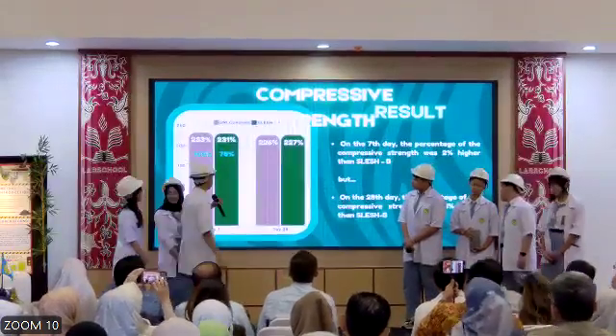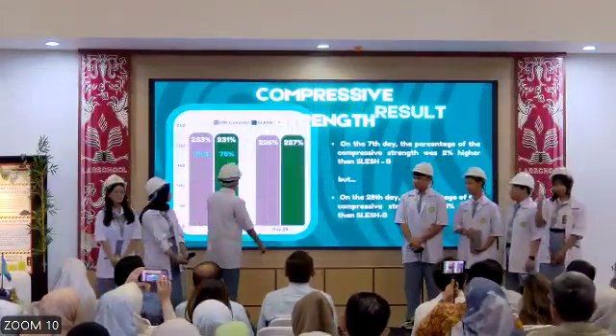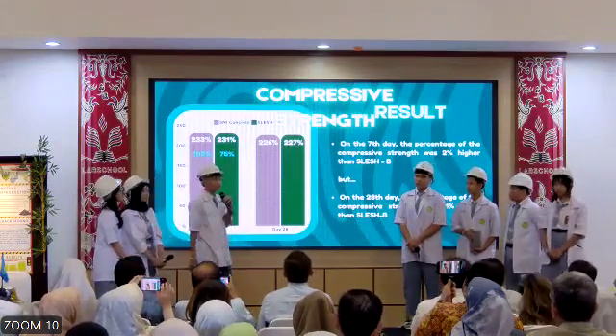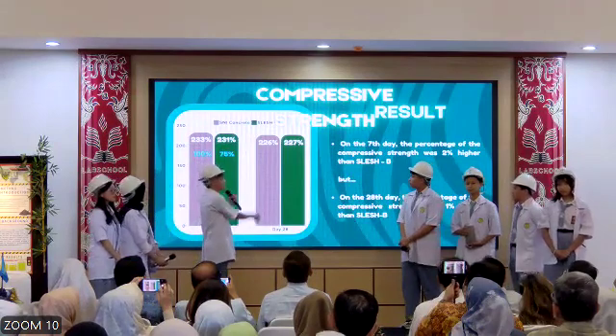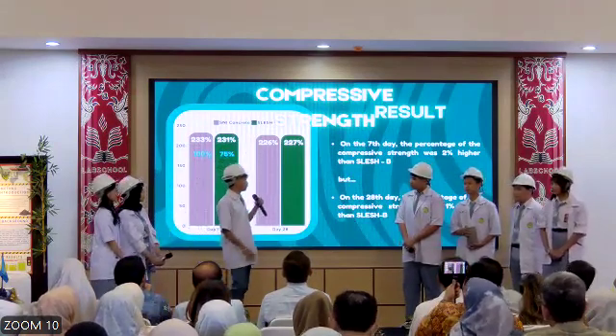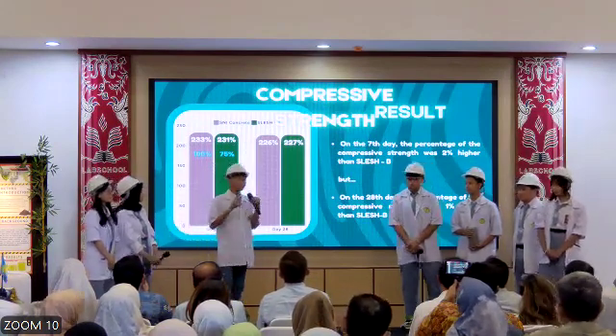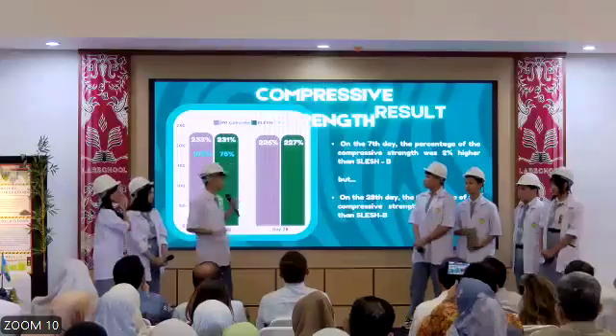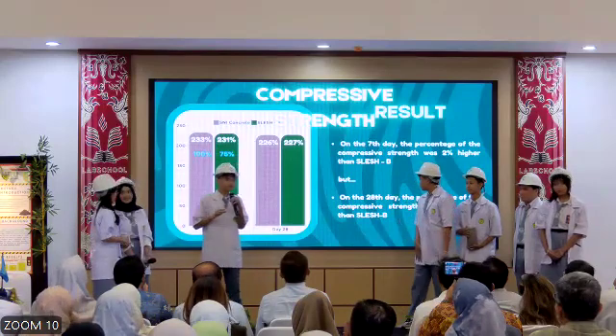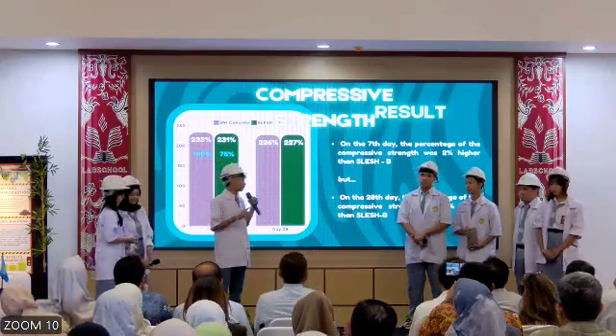Okay, so here are the results of the compressive strength test. The gray one is the normal concrete that uses 100% of cement, and the green one is our concrete that only uses 75% of cement. On day 7, the percentage of the compressive strength was 2% higher than SLESH-B. But on the 28th day, the percentage of the compressive strength was 1% lower than SLESH-B.